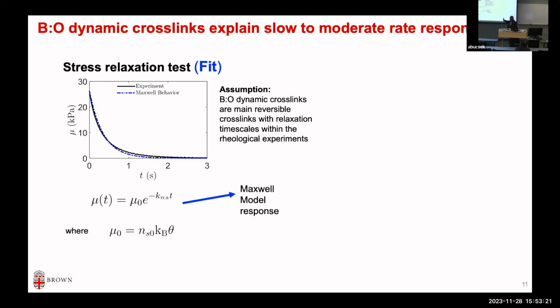So what we have done is first order kinetics, the basic assumption of first order kinetics, to define the boron oxygen. There's one crosslink, the dynamic crosslink that's being formed and broken. Then we did the stress relaxation experiment. This is in oscillatory rheology, like in the rheometer. All you do is apply a constant strain and watch the stress go. That's very viscoelastic behavior, right? And if you look at the first order kinetics, the shear modulus will come out to be like this with one parameter, and we can fit this rate parameter using the experimental data. So there is the fit.